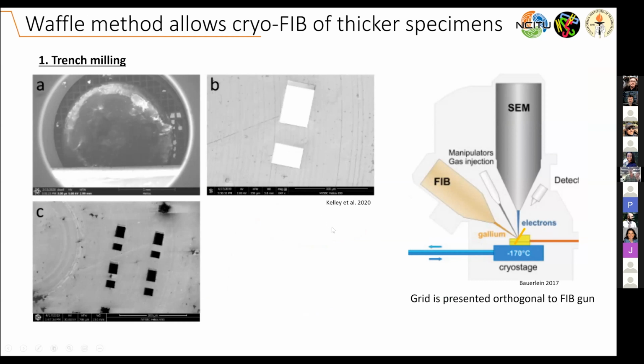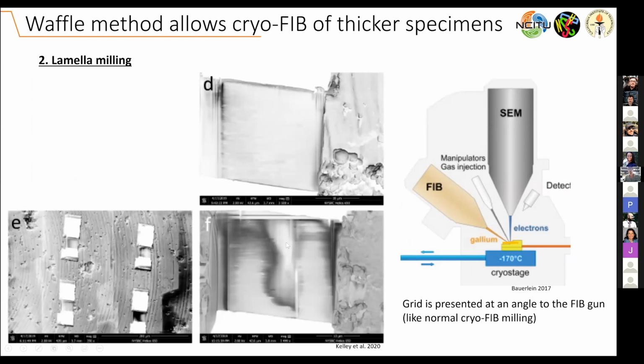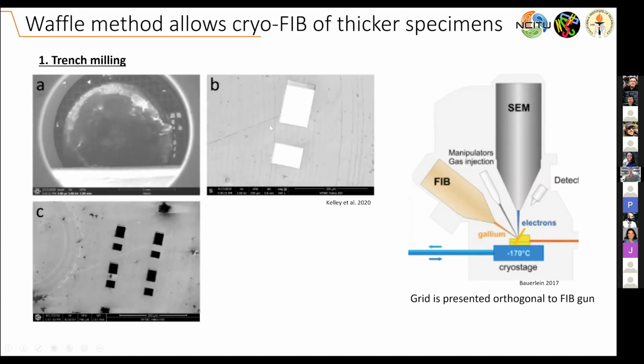And so the waffle milling has a first milling step called the trench milling. So here in A, you can see the waffle. In B, you can see the trench milling. So when we trench mill, we present our grid, which is here, this orange stick, orthogonal to the FIB gun. And so we mill directly straight into the sample to clear out all the thick material that is around this wedge right here. And then we tilt the grid at a specific angle, and we proceed at doing regular FIB milling on this little block that was previously cleared out.